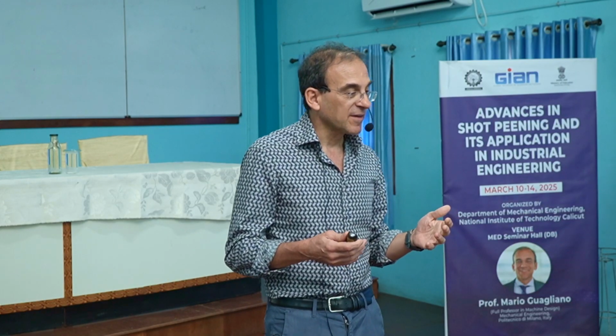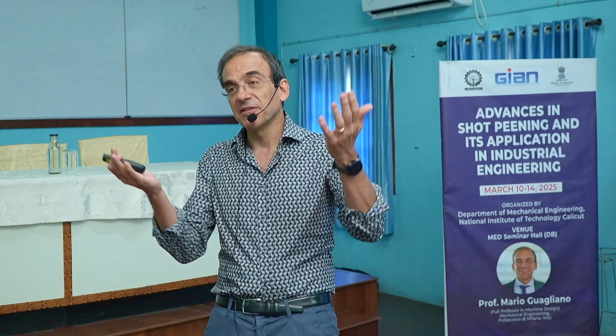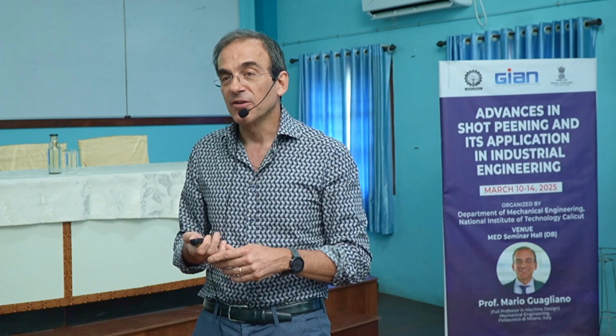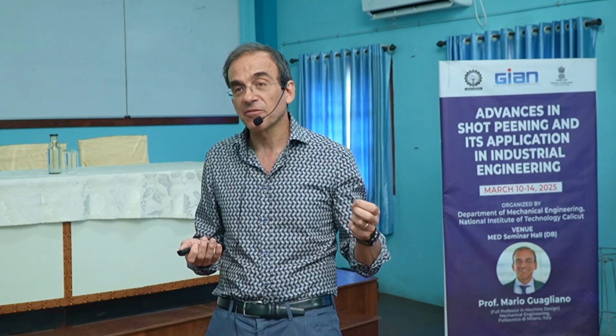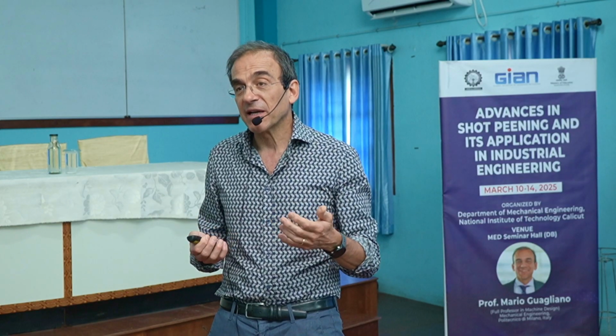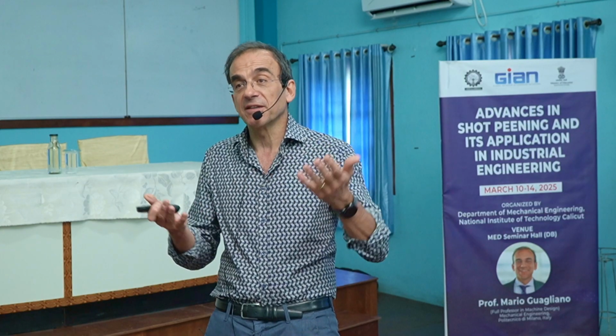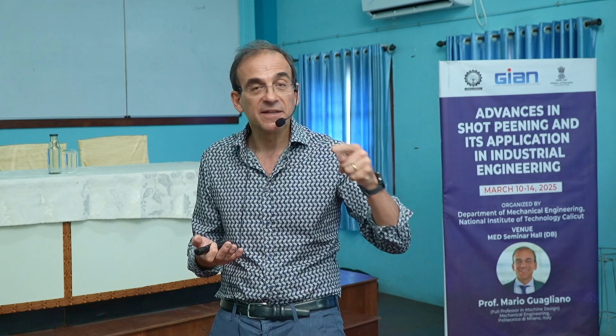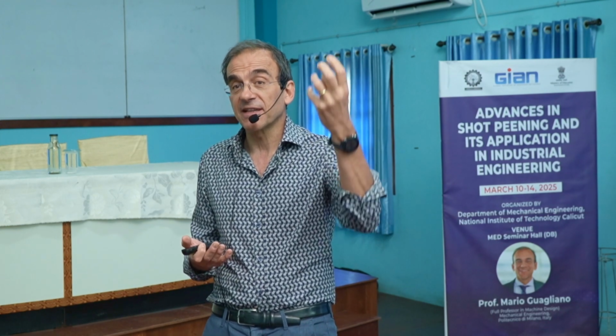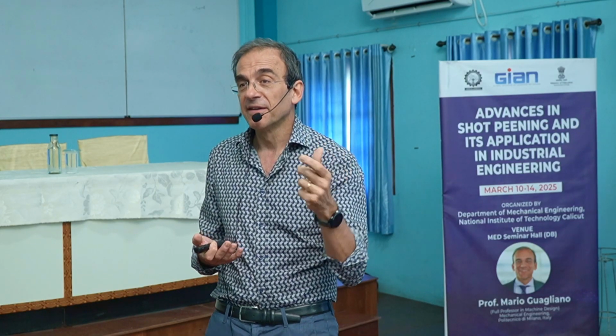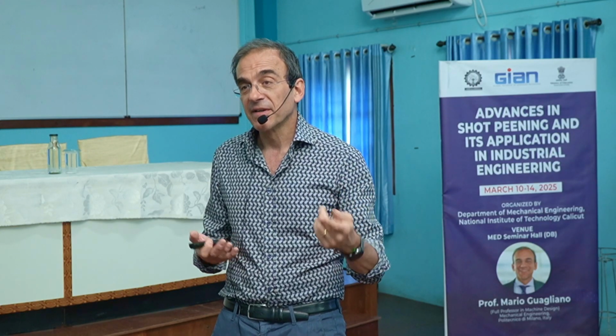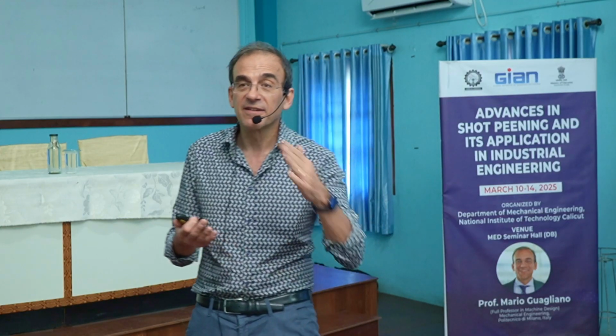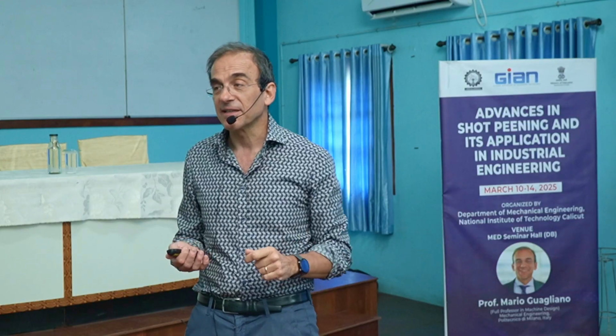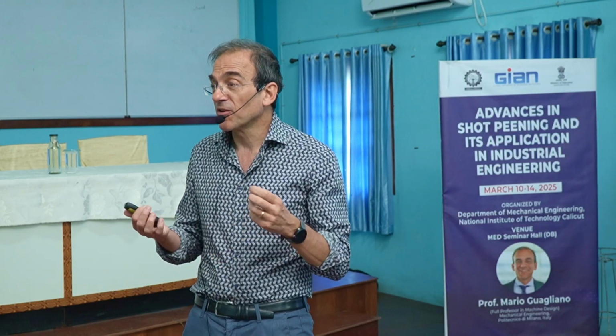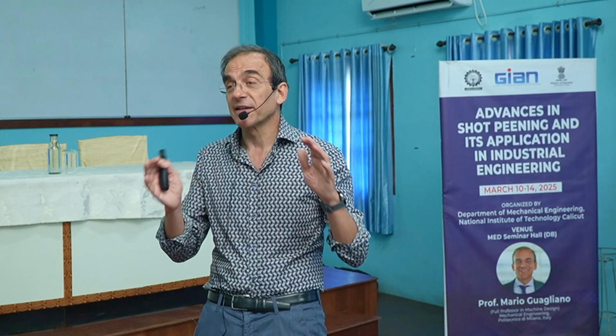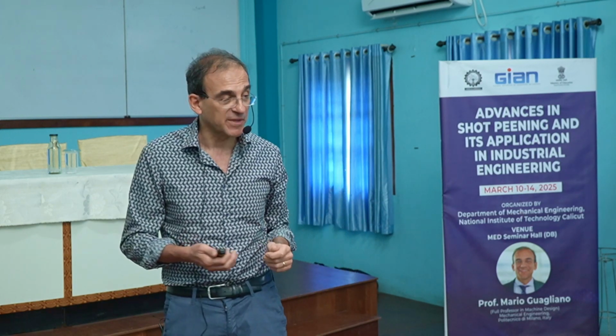Larger shot reduces roughness. Indeed, if we must choose the shot diameter and we think of the surface roughness, larger shot makes it possible to reduce the effect on roughness. Why? Because if we have a small shot, and the kinetic energy is the same, the force will be concentrated in a small area, and so the indentation will be more severe. If the diameter of the shot is larger, we'll have an indentation that is a bit flatter, let's say. Okay, but many times we cannot choose the shot just for the roughness. We have other geometrical constraints that somehow limit the range of dimensions we can use.